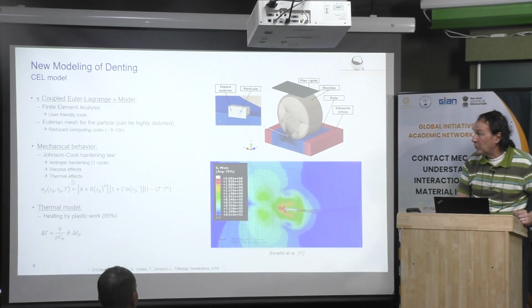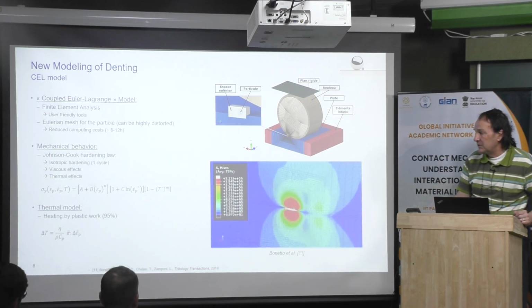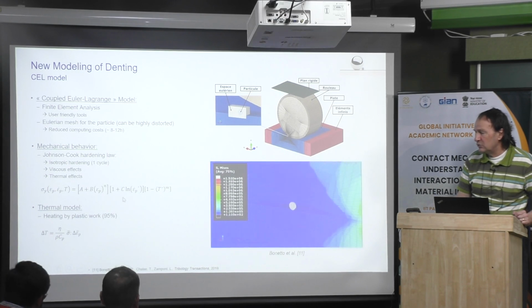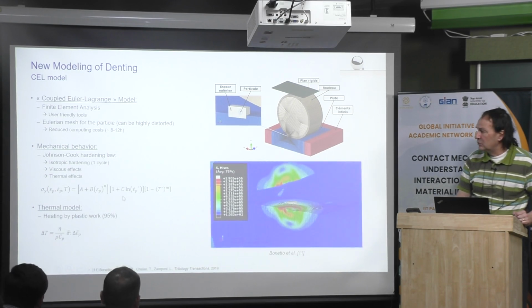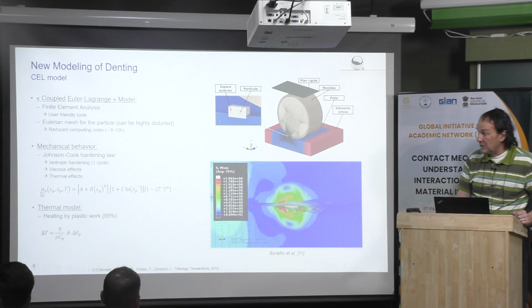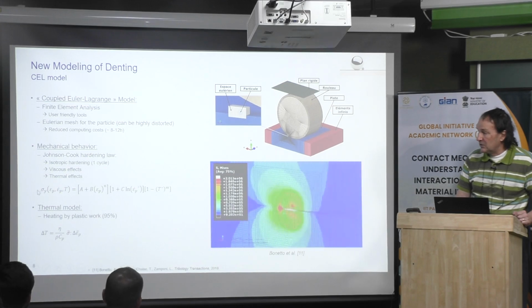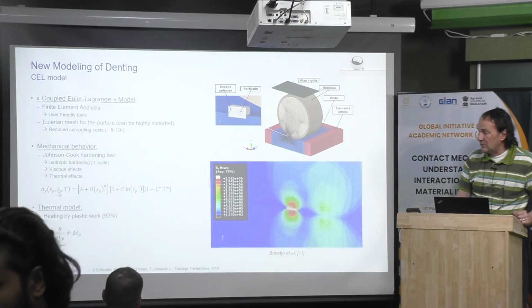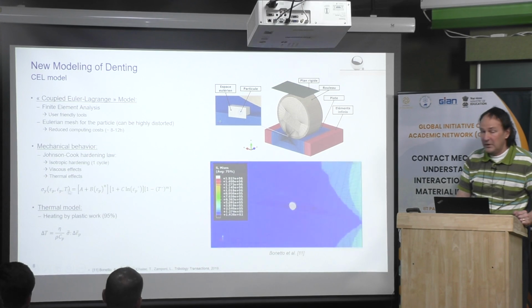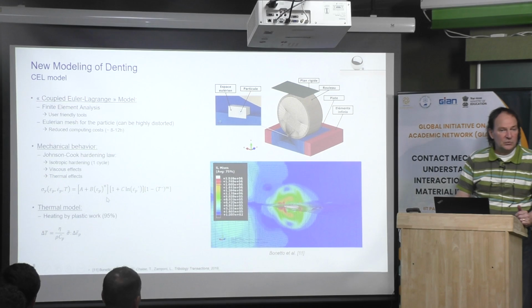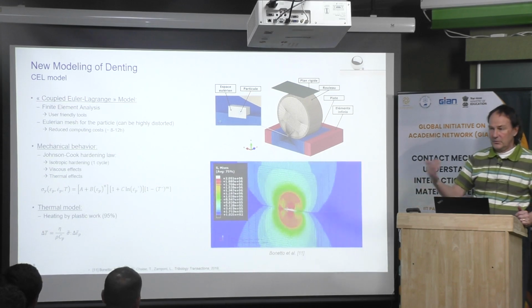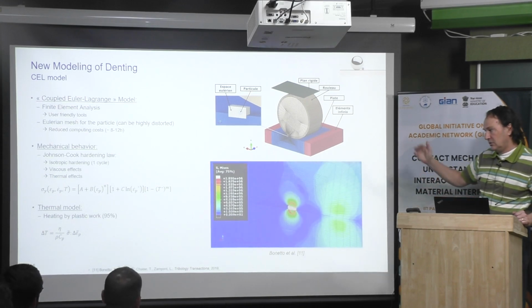Now you need properties. This is one of the difficulties. Then here we decided to use a Johnson-Cook model. The Johnson-Cook model gives you the yield strength depending on the plastic strain rate and the temperature. Okay? In fact, this model is mostly empirical. You have to take that from the literature.